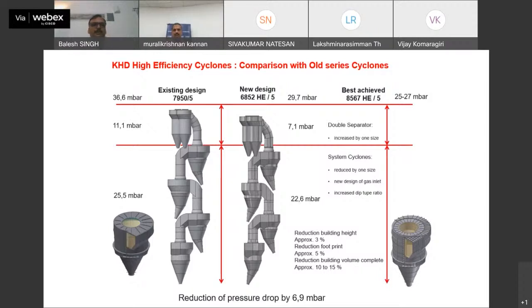So we can see here the earlier designs, the pressure across the preheater was 36.6 mbar, but in the same equivalent series, that is now well achieved up to 25 to 27 mbar at the preheater exit. So this is the development that means now we can think the preheater exit pressure can be maintained at less than 30 mbar. That means 300 mmWg.